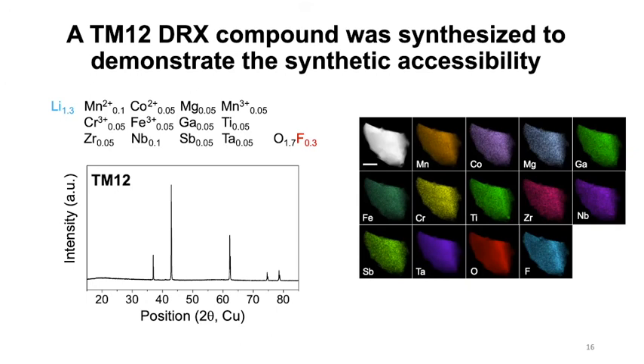And these experimental results demonstrate that the DRX material actually has very good structural stability against disordering, which allows us to incorporate various different transition metal species to improve the lithium transport. However, we have to note that this composition is not optimized for better electrochemical performance, but just serves as a proof of the synthetic accessibility of super high entropy DRX materials.